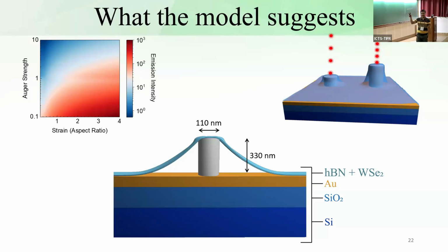I'll show you the spectral one. I do not have an answer to what kind of structure we're talking about, but I'm pretty sure these are all point defects about 200 meV below the exciton gap. So these are not mid-gap, but somewhere around 200 meV below the exciton gap.